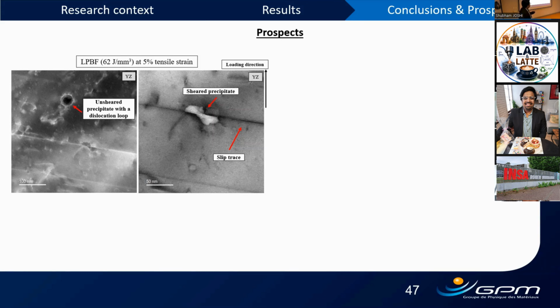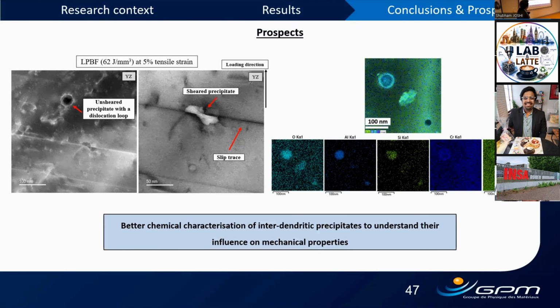This is not very common, but we saw in one of the micrographs that it interacts with a slip trace. And the EDS analysis of these oxides shows that there forms a chemical segregation in terms of core and shell. So somehow, maybe these oxides could also be influential on mechanical properties. So it would be really interesting to take up as a challenge.